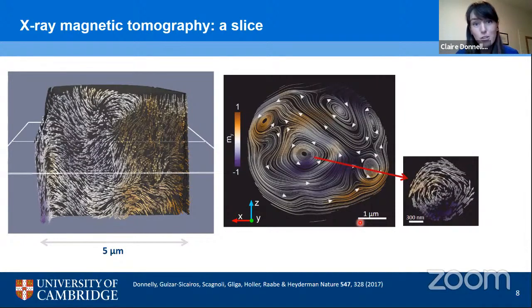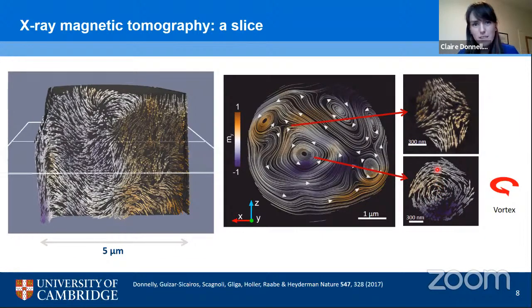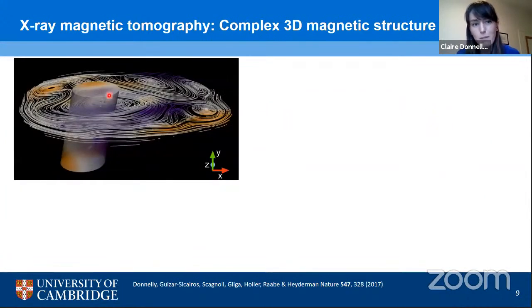We have topological objects such as vortices where the magnetization curls around a central point. And in this point, the magnetization can point in or out of the plane. We also have anti-vortices where it's a more saddle-like structure, again with a core that can point in and out of the plane. However, this shows us that we've got quite a complex network of topological objects, but it's a very 2D way to look at a 3D data set. So what we next go on to do is look at a subvolume of our structures. Specifically, this volume indicated that surrounds the central vortex of our pillar.